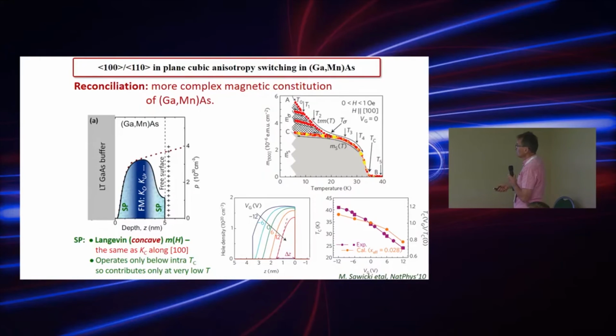So they are also depleted of holes at the free surface, and near the low temperature gallium arsenide buffer. As a result, the ferromagnetic coupling is maintained only in the center, where the hole concentration is high enough to support ferromagnetic coupling. Otherwise, on both ends, near the surface, there is no long-range ferromagnetic coupling. The coupling is maintained only over short distances, so we have superparamagnetic-like properties.